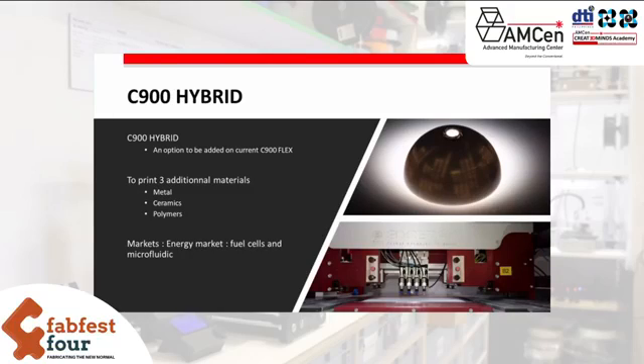But the most important point about hybrid printing, which we can also call multi-material printing, is that you have to keep in mind that printing is just one step. After, you have to do debinding and sintering. And during the sintering step, you will have some shrinkage. So if you print a hybrid part, all the components inside must have quite the same shrinkage in order to avoid any cracks or decohesion during the sintering step.